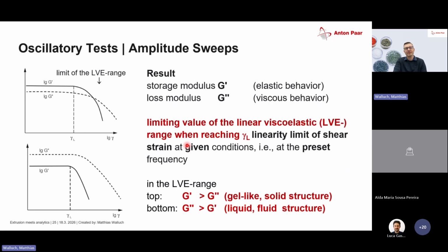So just a look at what happens during an amplitude sweep. Again, we have one test point to the other, so we just increase the amplitude from left to right, and we can see two things here. In principle, we see that G prime, which is the storage modulus, so this is the elastic behavior of the material, stays constant over a certain time, and then it starts to decrease. So this means at this point something happens, and this is that we break up the inner structure, so the material is not able to relax anymore and to get back to the original state. So everything that we want to do should be done within this area, because after this point, if we apply too high a strain, the material will be destroyed and we don't get correct data anymore after this.